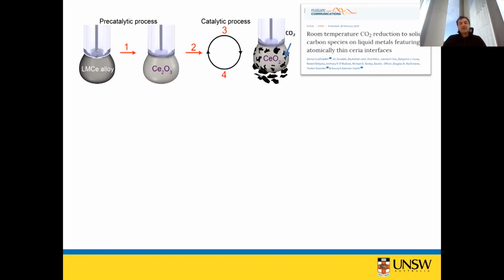It produces really thin, not fully stoichiometric cerium oxide, so Ce2O3, on the surface. And we put everything in a secondary liquid with bubbled CO2 gas. So CO2 gas comes around this, and we apply the voltage. This CO2 gas breaks down on the surface and produces stoichiometric CeO2, fully oxidized cerium oxide. But this applied voltage reduces the surface back to Ce2O3, so it continues.